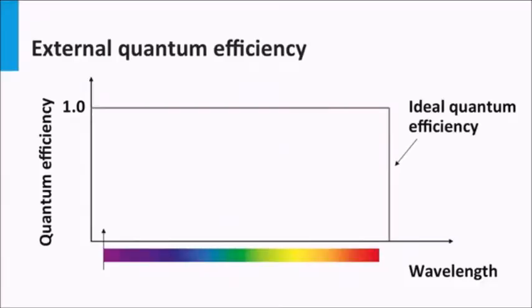Let's say we have a material with bandgap E gap. The ideal external quantum efficiency would look like this graph. Note that the horizontal axis is plotted in wavelength. Smaller wavelengths correspond to higher energetic photons, the blue spectral part. Longer wavelengths correspond to lower energetic photons, the red spectral part. Above the bandgap, all photons result in a collected electron, or in other words, the EQE is 1 or 100%. In reality, the EQE is always smaller than 100% and its value varies with wavelength.